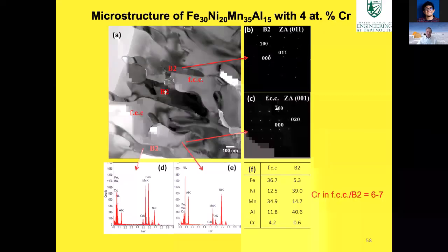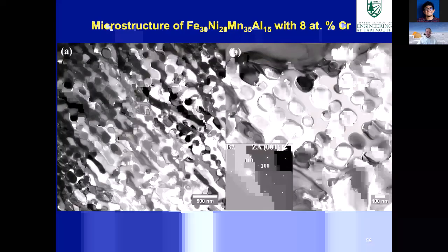We looked in the TEM at these microstructures, and again confirmed the B2 and FCC. If you look at the chemistry, what you find interesting is the chromium pretty much all goes into the FCC phase. So it's probably the FCC phase that's showing the brittle behavior. This, by the way, is the 8 atomic percent chromium, which has quite a different microstructure, but it's still FCC and B2.